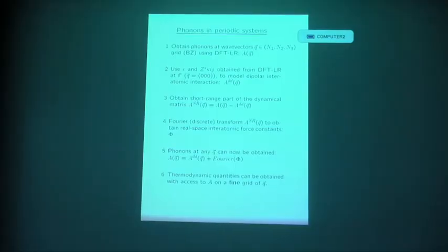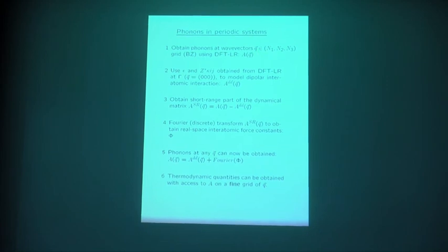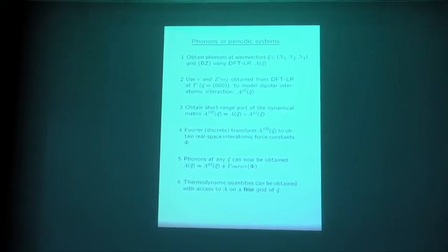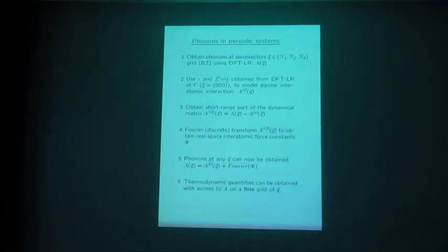Where did the supercell idea go in the linear response calculation? In the response calculation of the phonon spectrum, you calculate it at wave vectors on a mesh, N1 times N2 times N3. In the frozen phonon case, that's the supercell size. So suppose I use a 2 by 2 by 2 mesh for phonon calculations, it means I'm using a 2 by 2 by 2 supercell in a frozen phonon calculation. So you will have to use finer and finer Q point mesh if you want to go to a bigger supercell. But your calculation will be with one unit cell.